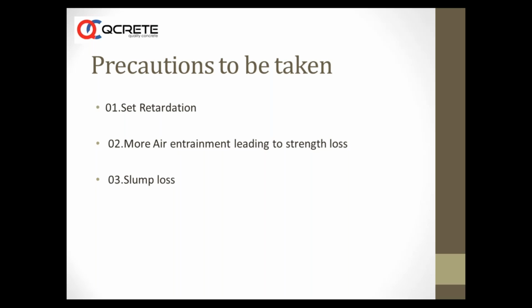If the truck mixer is turning faster at very high RPM, that can also cause slump loss. Most importantly, if the quality of gypsum used in cement is hemihydrate or anhydrate, it absorbs the admixture and will not allow the admixture to work the way it should. In such cases also you have slump loss problems.